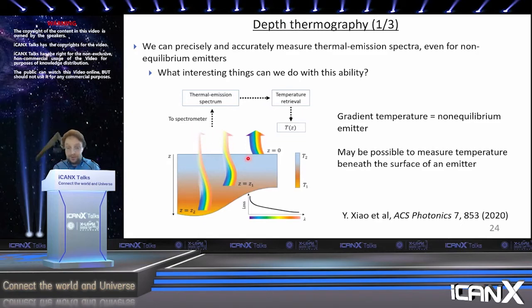So your temperature is not well-defined because you have many temperatures, and your emissivity is not necessarily well-defined. But what you can do in these circumstances is measure the spectrum of thermal radiation. And if you can do that very well, you can try to use computational techniques to retrieve the temperature as a function of depth. Because, for example, the thermal radiation from the surface is going to have a different spectrum